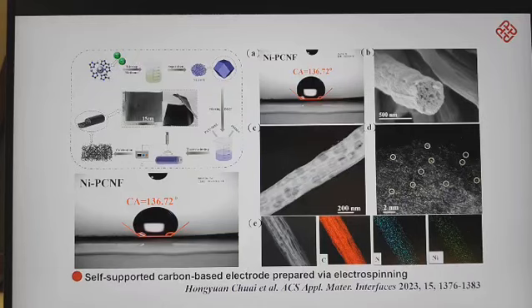At first, we introduced an organic pore-forming agent, PMMA, and nickel-doped ZIF-8 as a nickel source into the precursor, PAN sol-gel. After electrospinning and high-temperature calcination, we obtained the self-supported carbon-based electrode with nickel-nitrogen active sites. From the SEM images, we can clearly see that during high-temperature calcination, PMMA completely decomposed, forming open-ended through pores in the carbon fibers.